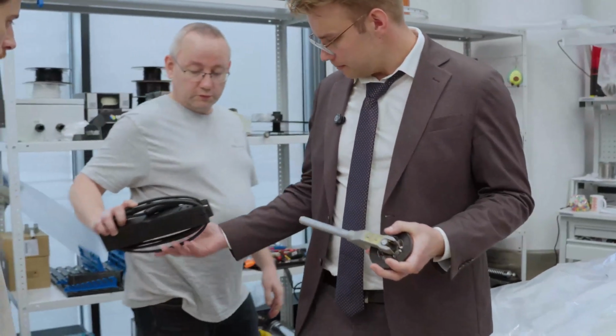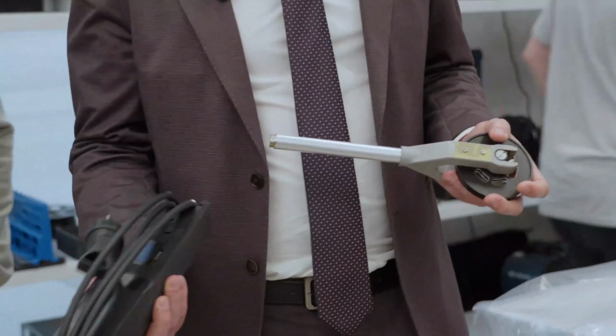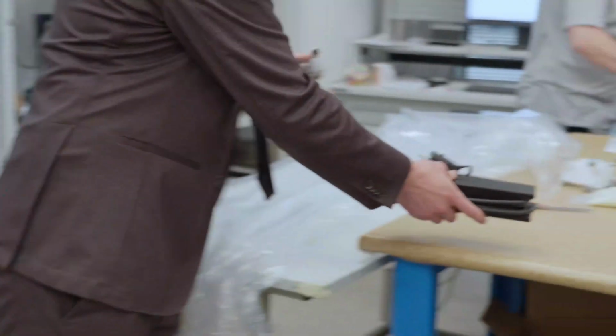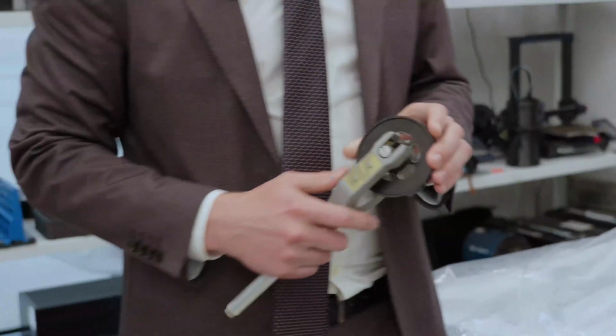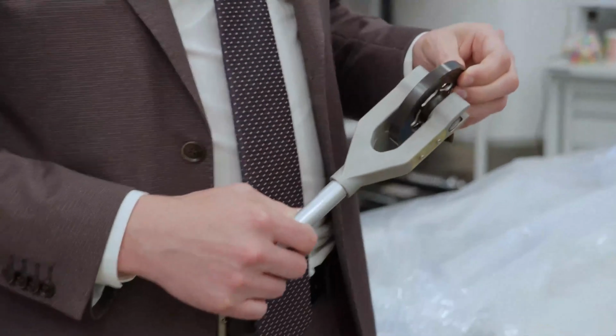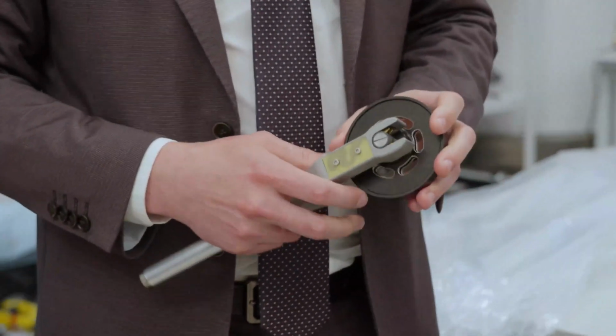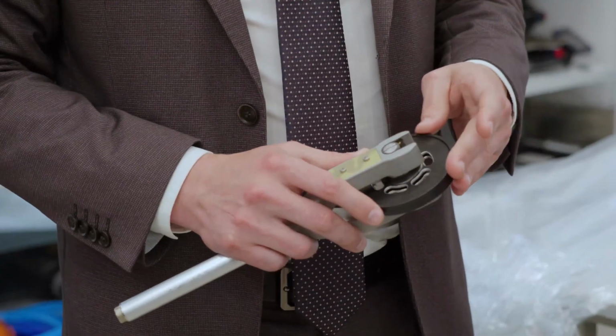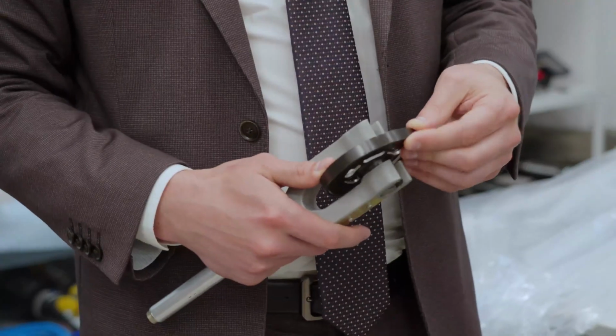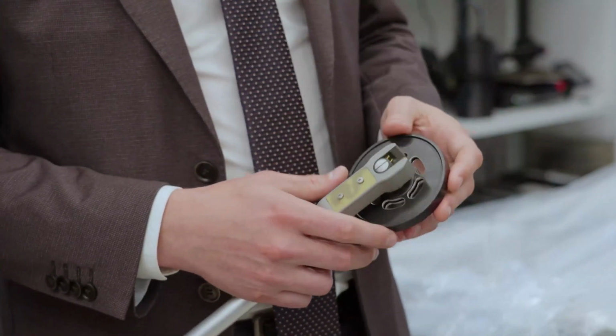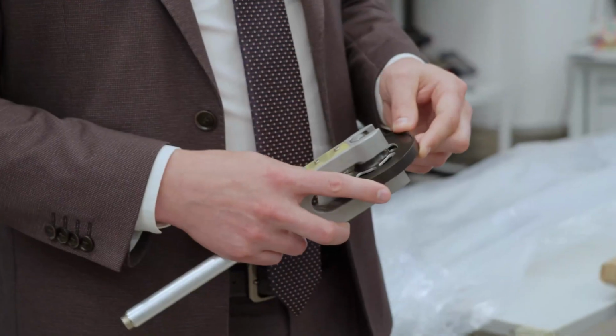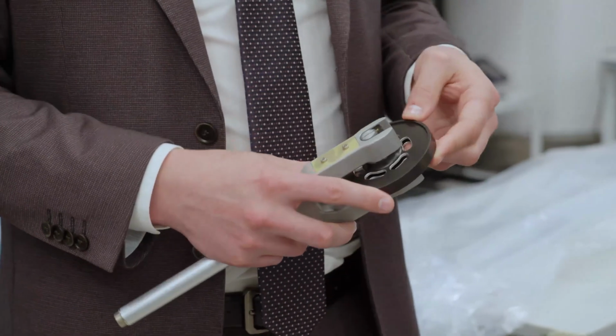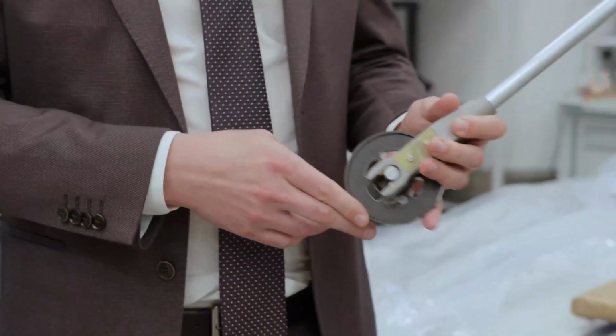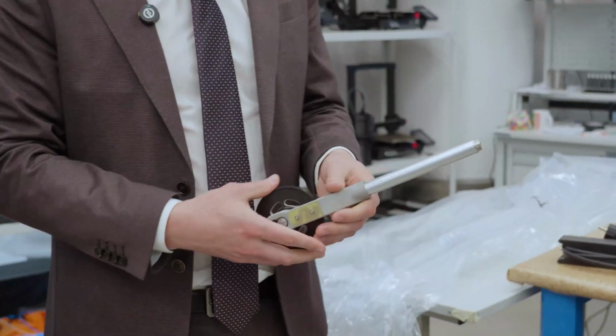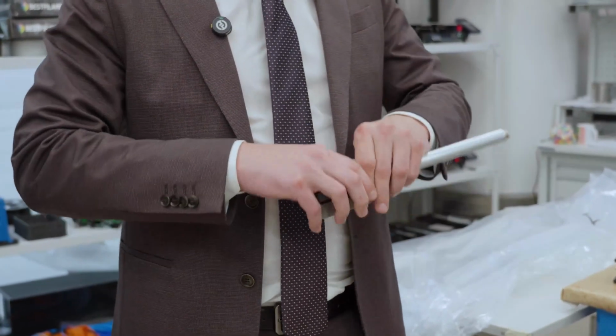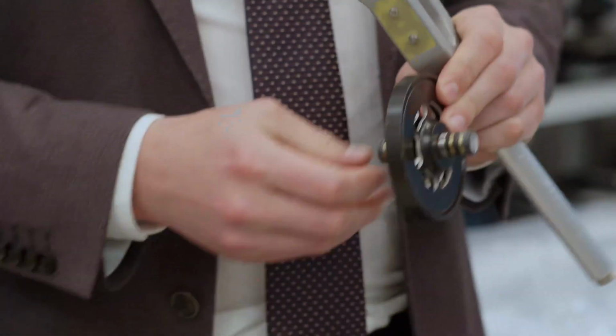There's a control unit for it, which also supplies power. Here is this roller. It's currently in the final stages of development. It already welds, and our colleagues have made several products with it, but they discovered a number of shortcomings during operation. For example, the edge of this roller is exceptionally sharp and unrefined. When the seam is pressed with this particular roller, its overly keen edge causes a noticeable and undesirable thinning of the material. This thinning acts as a stress concentrator, but otherwise the roller is quite convenient.